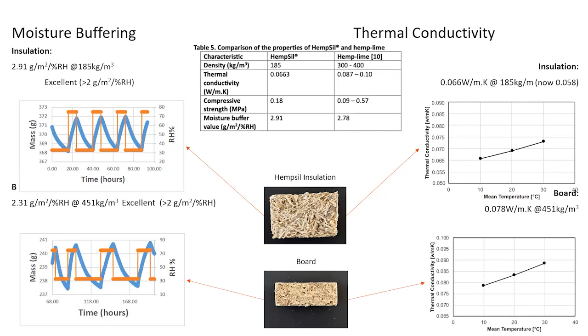But the key thing is the moisture buffering, where if you get moisture buffer levels of above about 2, wherever your figure is here, above 2 is what they call excellent. Well, we're at 2.91. We're well over the excellent. And what that means is that it manages the change in humidity really effectively. We've also got very low thermal conductivity values, so it's managing the internal thermal environment.